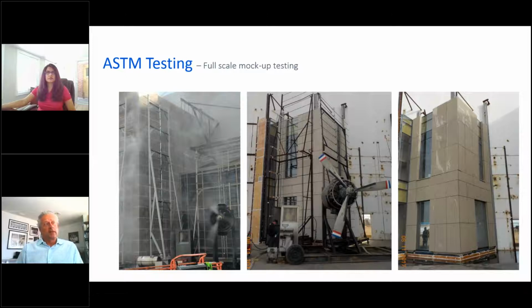The one on the left is the Air and Space Museum in Washington, D.C. And you can see this is testing the glass assembly integrating into the stone wall. And we actually tested it with driving rain with a negative air pressure on the inside. So it had a negative pressure that would allow kind of a sucking action on the water. So it was monitored to see how much the whole system could perform. The one on the right is another project that Afsheen was involved with the engineering on, and actually went down to witness the mock-up testing. And maybe Afsheen, you can elaborate a little bit on that one.